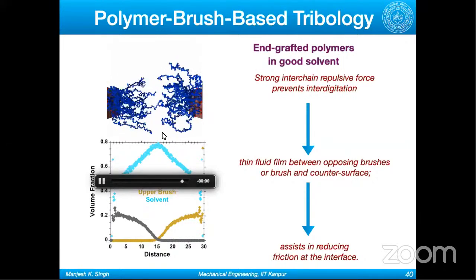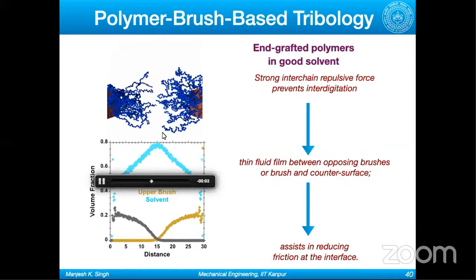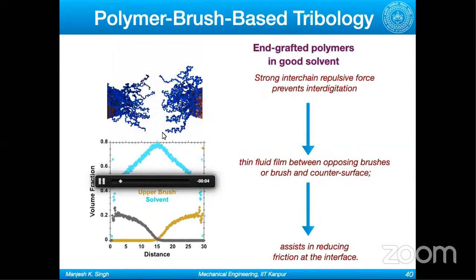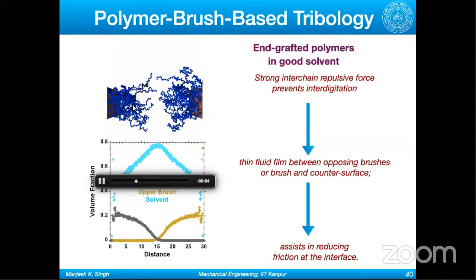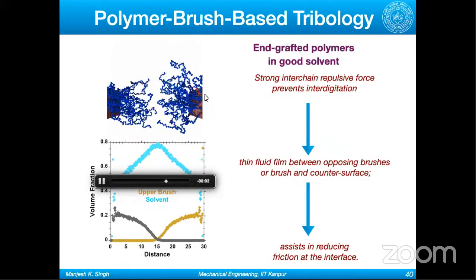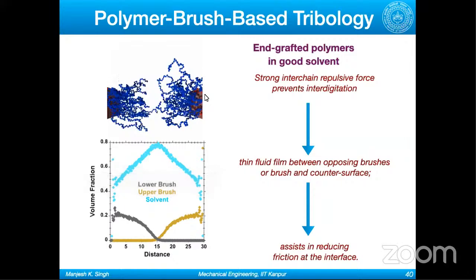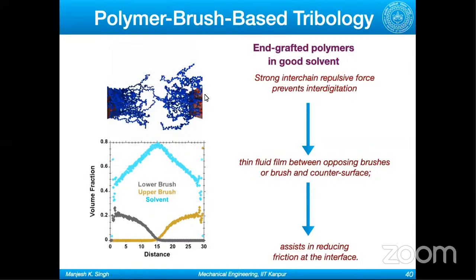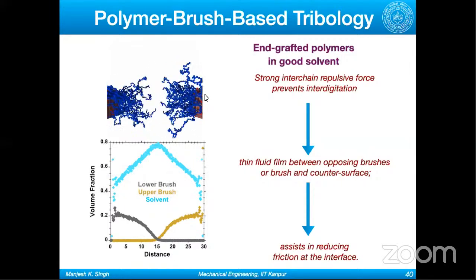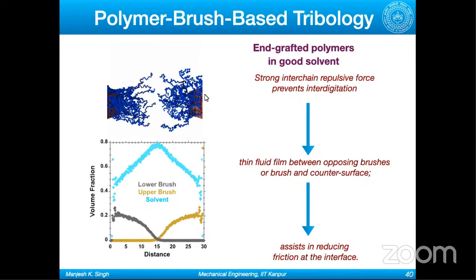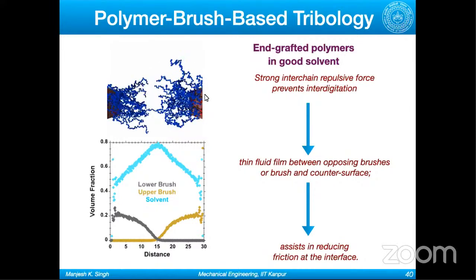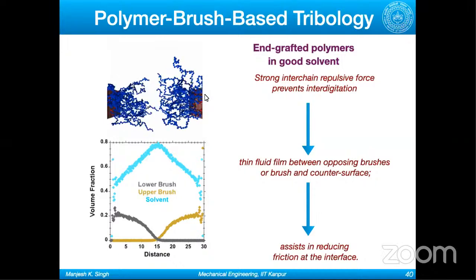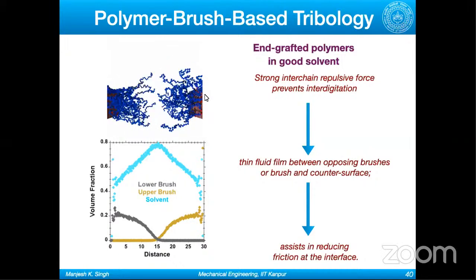So this way, if you have a hydrophilic polymer for which water is a good solvent, and you use water with this polymer, the polymers will take care of the load carrying capacity, and this water, because of its very low viscosity, will reduce the friction. If you have a brush against brush system, the friction will be so low that you cannot measure it with most of the experimental tools available today.